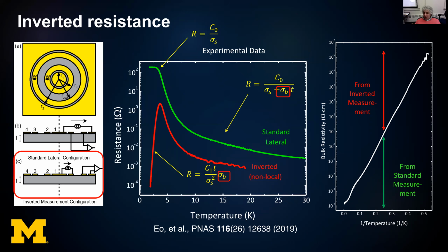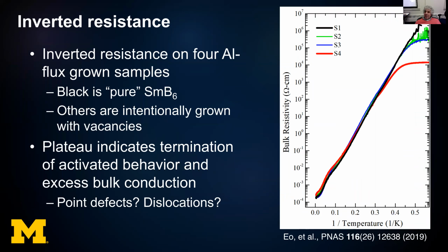And when we combine the whole data, we will be able to extract bulk conductivity over a much wider range of resistivity values. In fact, in this particular example, we managed to expand the bulk resistivity measurements by an additional 5 orders of magnitude. Now, we have used this method to characterize samples with vacancies, which were grown intentionally with different boron samarium ratios. We found additional conduction in some of the samples, the origin of which we do not understand, but over a wide range of temperatures, the behavior was found to be activated and rather immune to disorder.